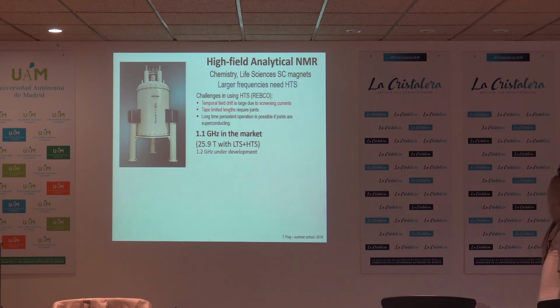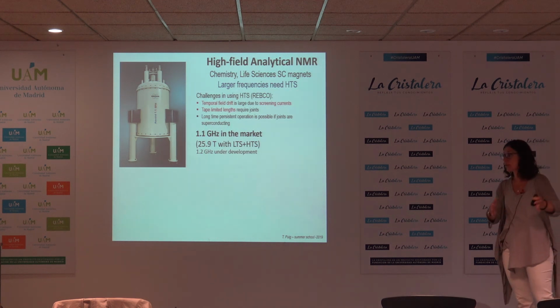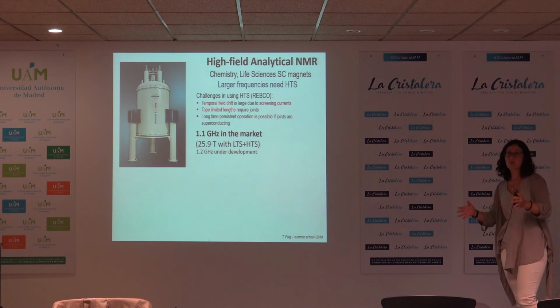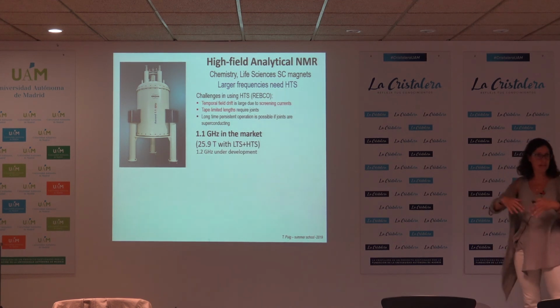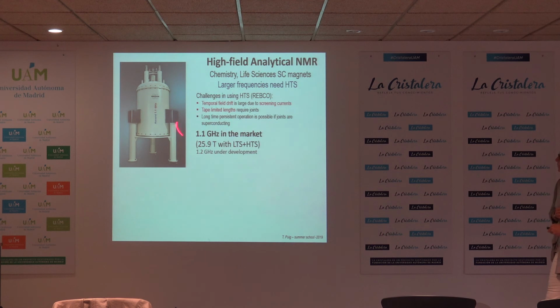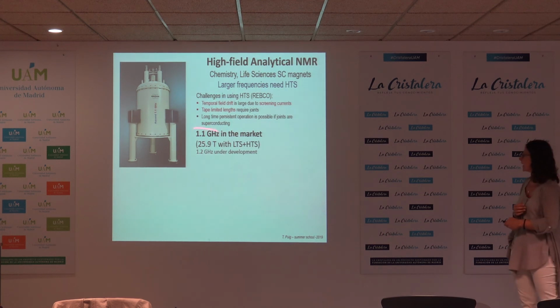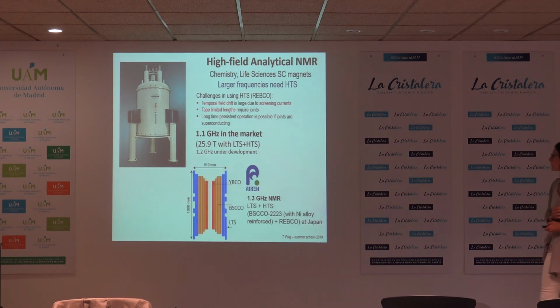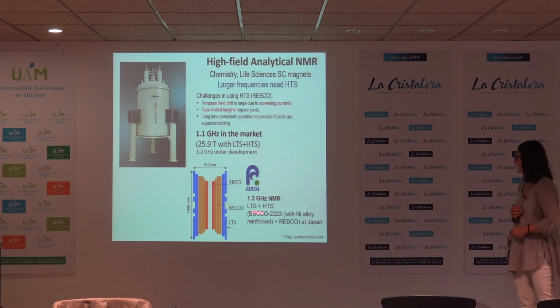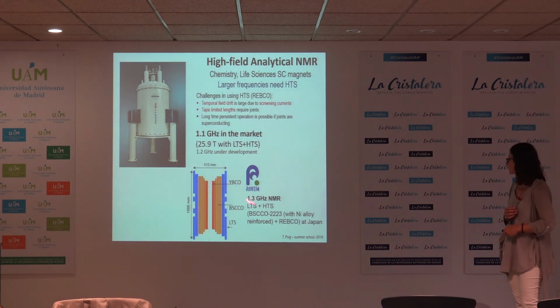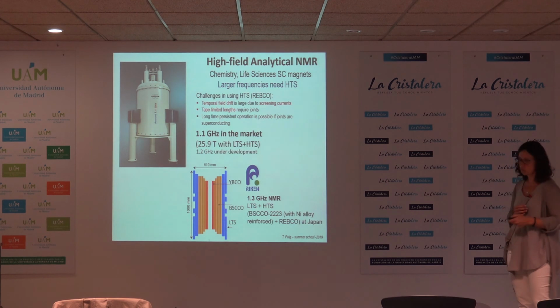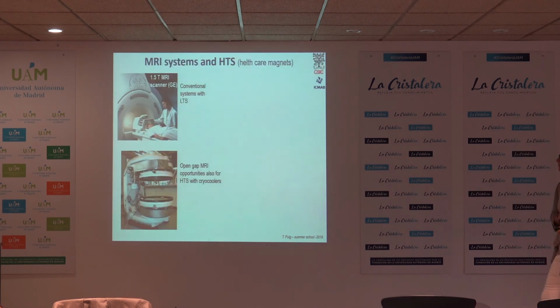Okay, up to 1 gigahertz you can do it all with LTS, so low temperature superconductors. If you want to go beyond 1 gigahertz, there's no way unless you also put in HTS. And at this moment they have demonstrated the 1.1. They are now developing the 1.2, and also in Japan they are developing the 1.3 gigahertz, which also would be a summation of LTS plus HTS.